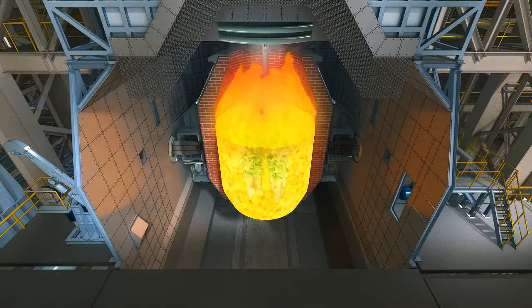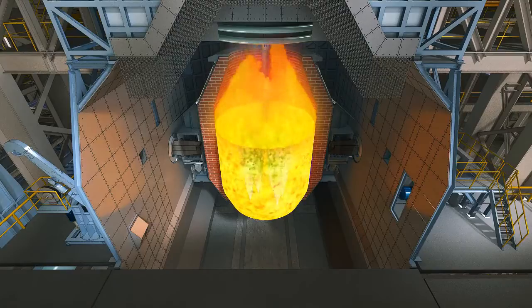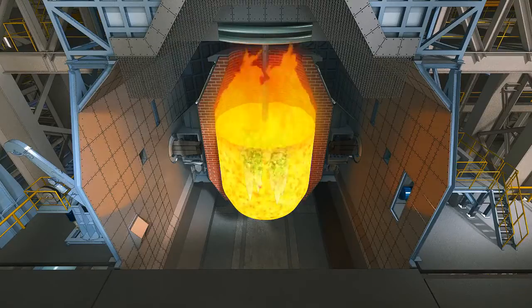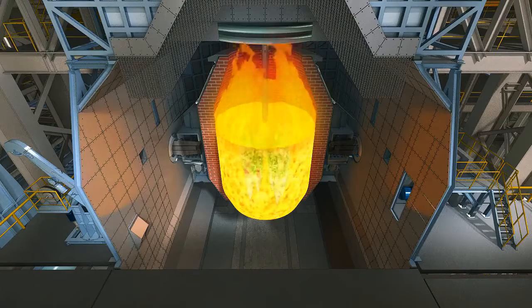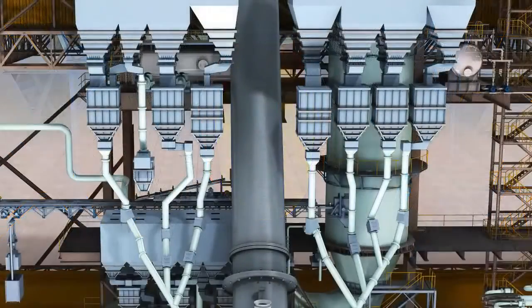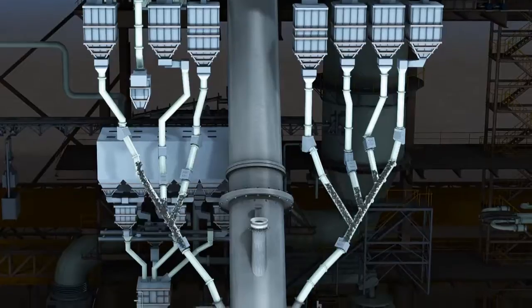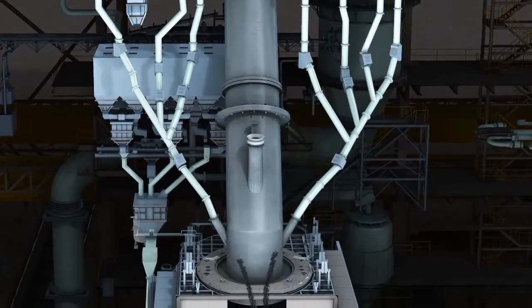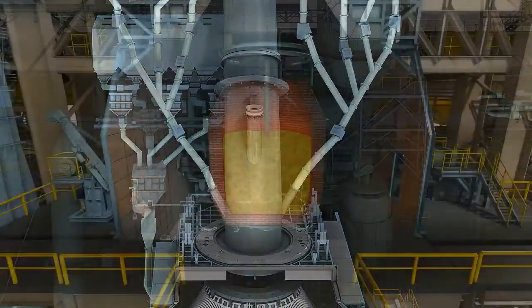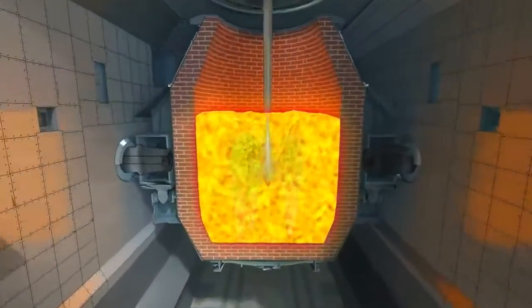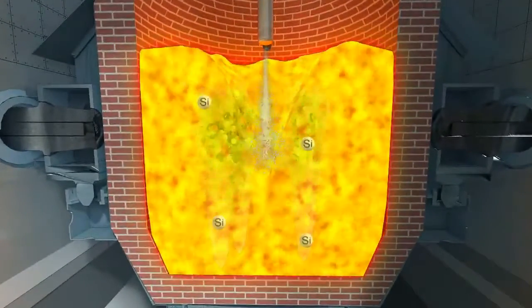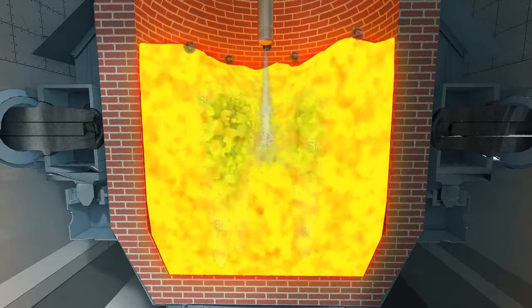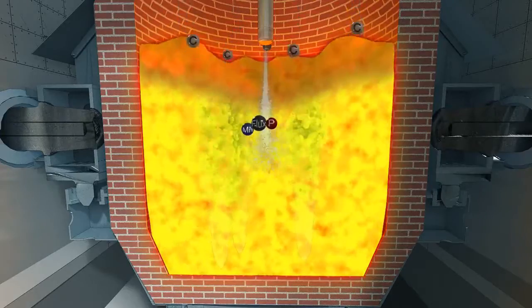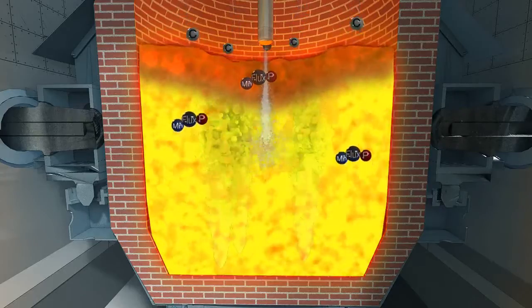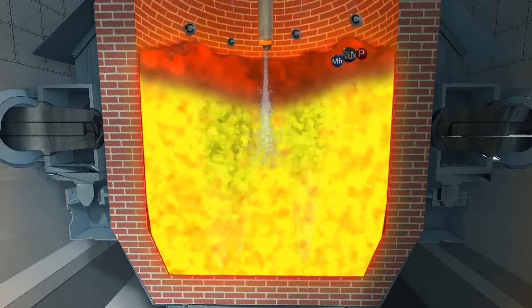When the lance reaches the designated position from the hot metal bath level through the main lance dome, the hot metal will be fired. The amount of oxygen and bottom bubbling gas will be set at a predetermined value. The weighed flux material will be injected after ignition. When the hot metal reacts with oxygen, silicon will react first, and the molten metal temperature will increase. Carbon will be released in the gas form, and manganese and phosphorus will react with the flux, and the impurities become slag.